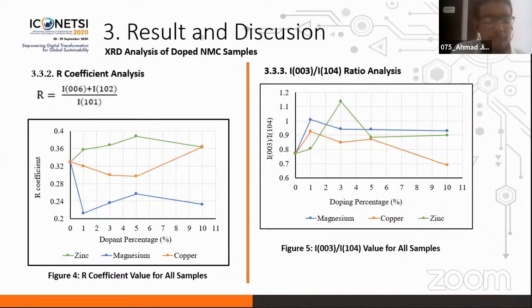Next is the I003 per I104 ratio analysis. To find out the inclination of cation mixing occurrence, we use the ratio of the 003 peak and the 104 peak. A higher ratio of this parameter leads to decreased cation mixing. Based on this figure, all of the samples have the possibility of cation mixing, but the lowest value of this parameter is for the NMC copper 10% sample. It indicates that this sample has the strongest possibility of cation mixing compared to the other samples.